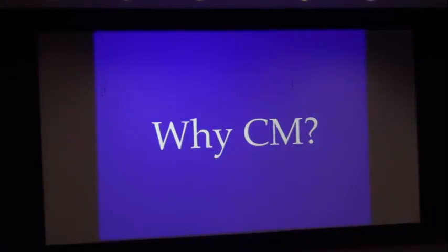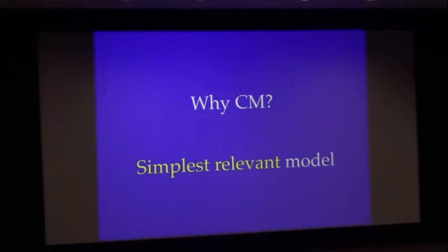He says, well, we have two full chapters on the co-rotational models that we left out of the second edition. And then he told me he regretted leaving them out, and this really changed my life as a rheologist. This is where it started. So first of all, he said, it's the simplest relevant model to your problem. You say, what do you mean by that? He says, well, it's the simplest model that actually predicts higher harmonics. The Maxwell model, the convective Maxwell models, for instance, predict 0 for the higher harmonics.